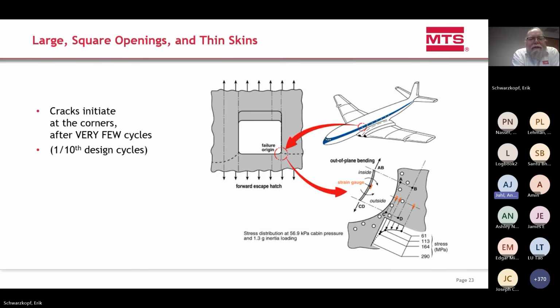The airplane had relatively large openings. The windows were normal sized for the time, and it had relatively square openings, though with rounded corners. These openings helped initiate cracks, and these cracks initiated at one tenth the design cycles, so far earlier than the models said they should initiate.